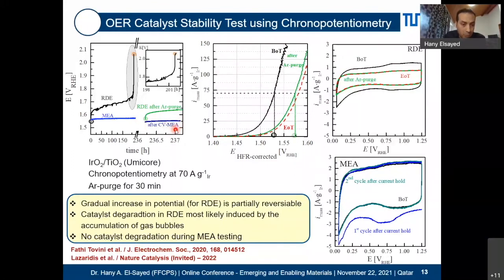And on top of this, after you finish the MEA testing, you find that the beginning of life and the end of life CVs are identical, meaning we did not lose any catalyst. So what is the conclusion here? The conclusion is, if you take the same catalyst and you do RDE testing, the conclusion will be, oh yeah, this catalyst is not stable. In reality, if you do it in the actual device, as you can see here, it is actually stable.